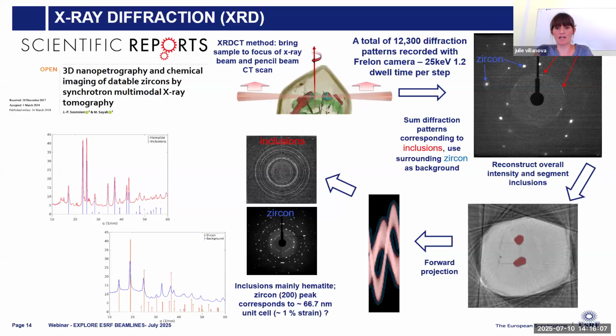By looking at and recognizing the different diffraction phases in those patterns, and then by also using some reconstruction algorithm, you are able to end up with this kind of slice reconstruction in which you can say, okay, here in white I have the zircon grain, and those red dots here are in fact the inclusions of some hematite that there was in those samples.